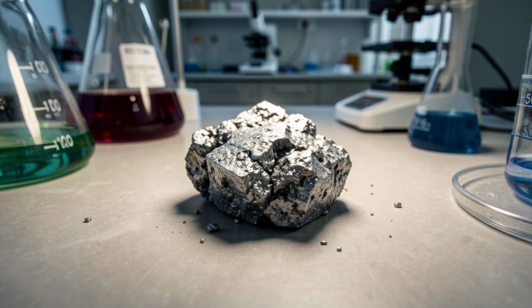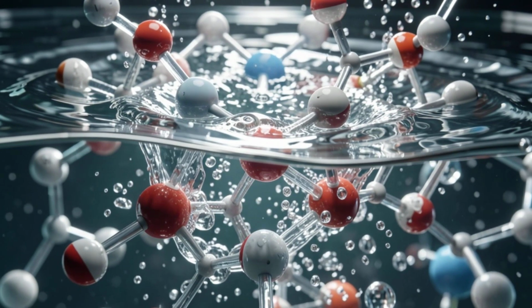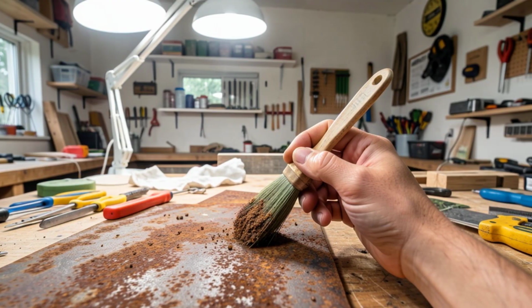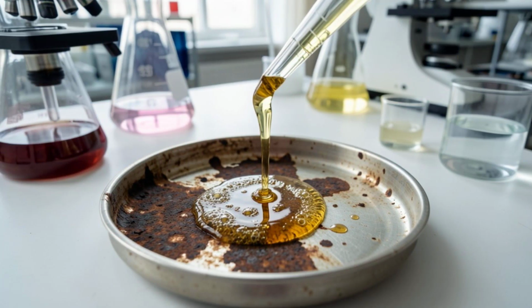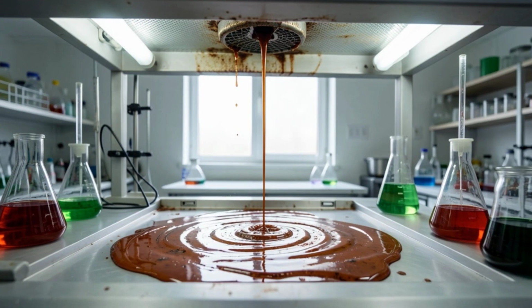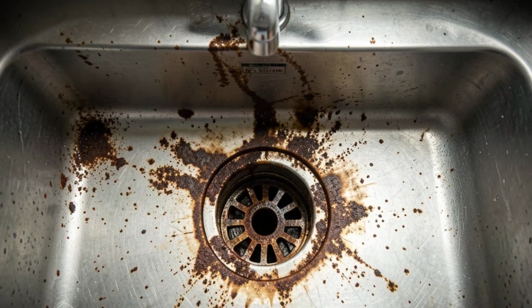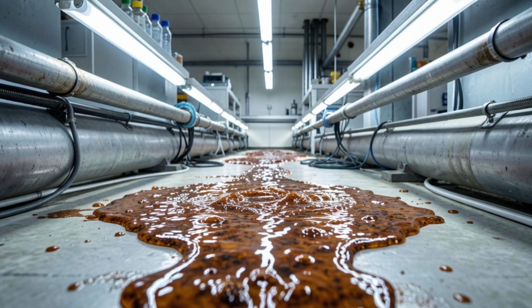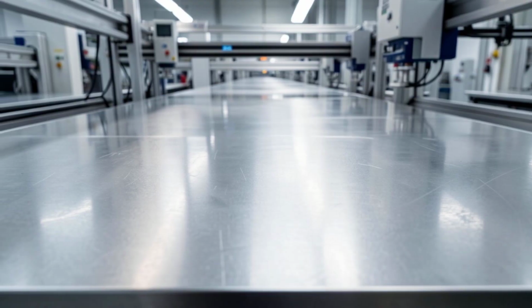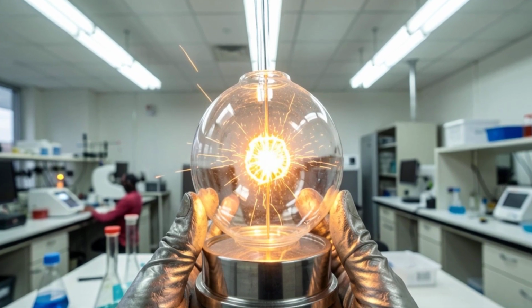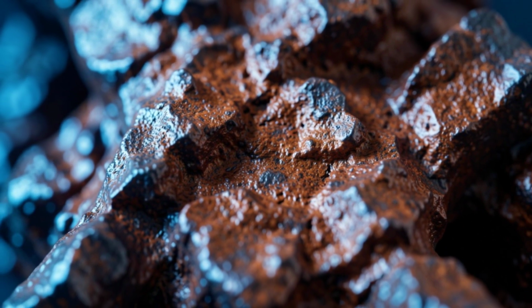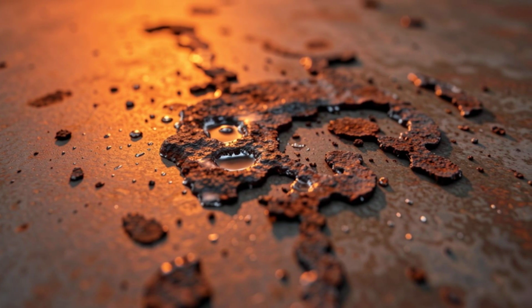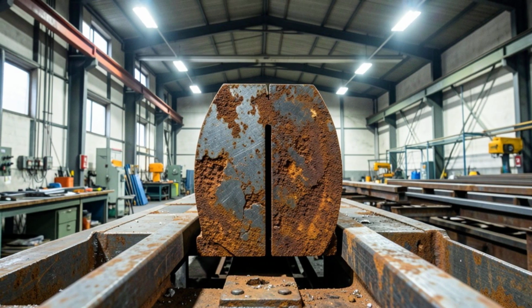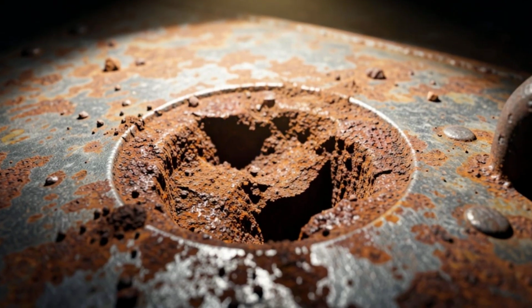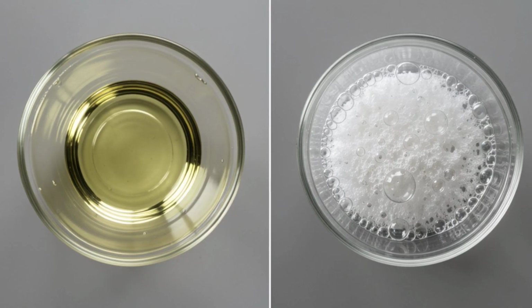When the acid soaks into that porous rust, it chemically converts the solid orange iron oxide into iron acetate, which is a compound that dissolves in water. So instead of fighting the rust as a solid the way a brush does, the vinegar simply turns the rust into a liquid and lets it wash away. And because the reaction targets the oxidized iron specifically, it works through the corrosion and stops at the healthy unoxidized steel underneath, lifting the rust out of the pits that no mechanical tool could ever reach.